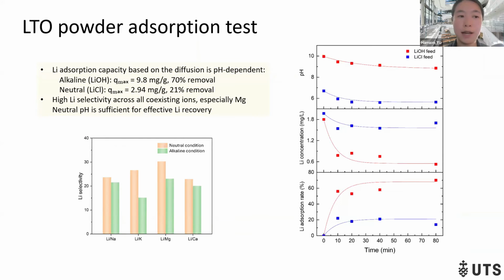So before the CDI test, we did the LTO powder absorption test, which is based on diffusion. The results show that the lithium capacity based on diffusion is pH dependent. In alkaline conditions, the capacity can reach 9.8 milligram per gram, but in neutral conditions, it is much lower. And then we found high lithium selectivity across all coexistent ions, especially magnesium. And neutral pH actually can facilitate the lithium recovery.